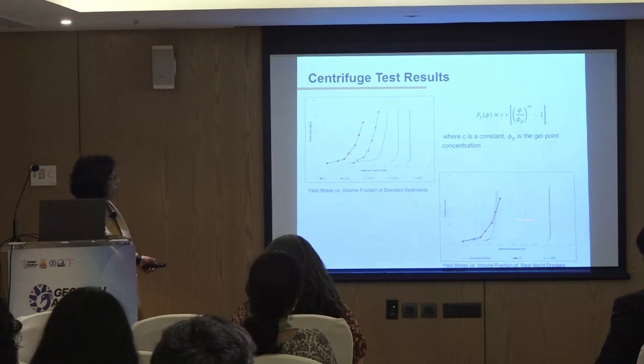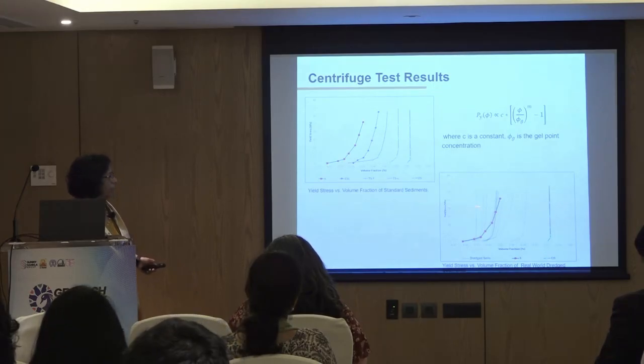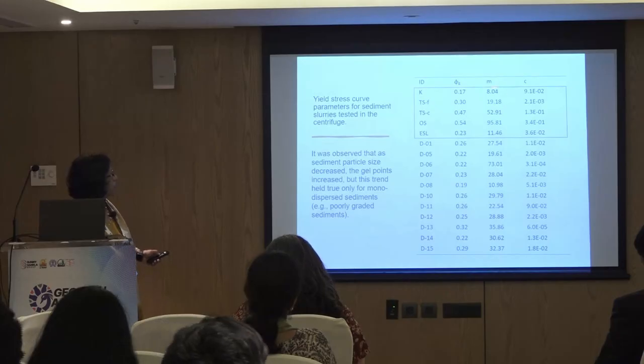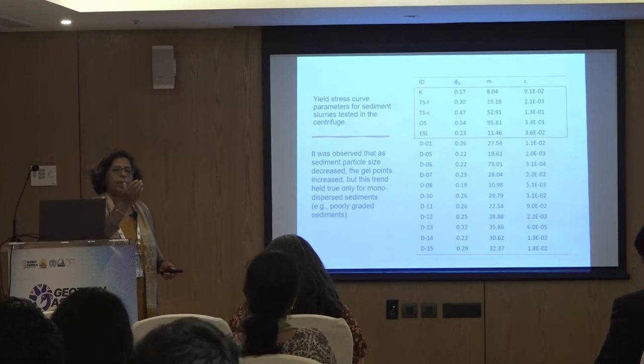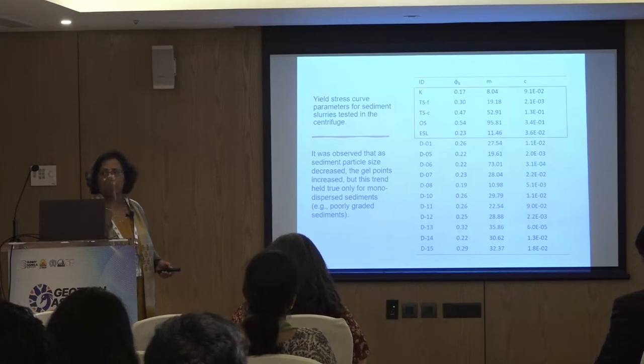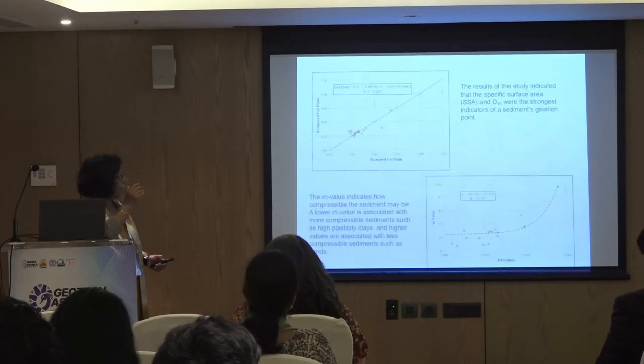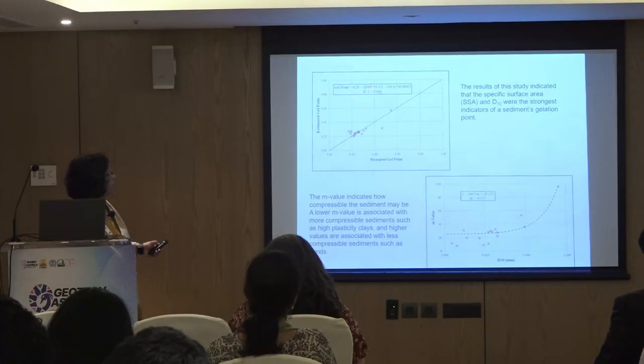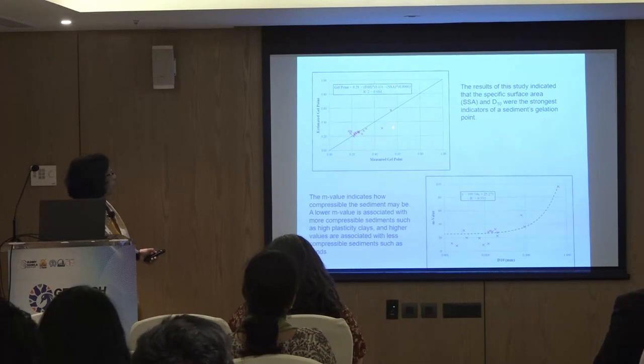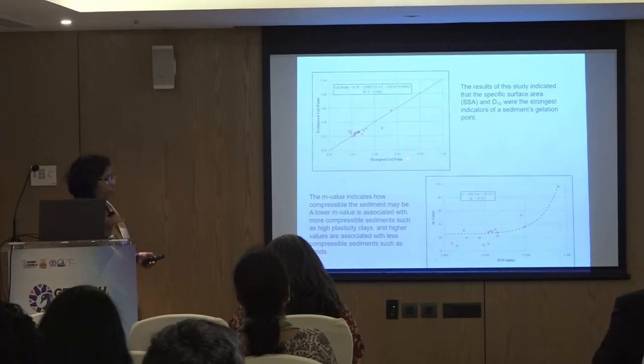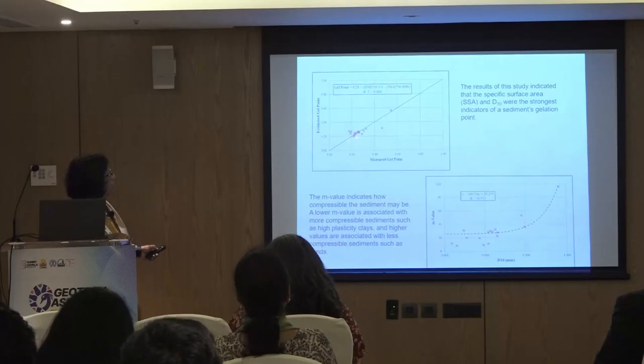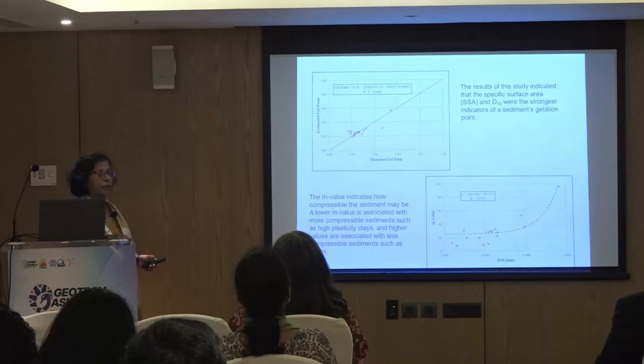So here are the test data for all these 25 or 50 sediments, and we don't even know the nature of the sediment. They vary widely. And when we look at these using this equation and looking at yield stress versus the slope, we make a clear observation: as the fine content in the slurry increases, the yield stress changes as a function of that. And then we found that the important parameters are D10 of the silt and specific surface area, both are interrelated. Finer are the particles, so we can find that this is the equation we came up with from our large amount of data. These are measured gel points from the centrifuge test. These are calculated values, and a reasonably good relationship. How can we use this? What is the value of that?